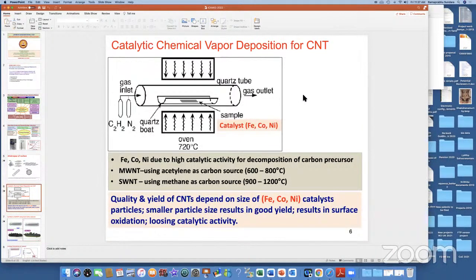So hydrogen will go out and carbon will get dissolved in the catalyst, and then one can grow either single-walled nanotubes or multi-walled nanotubes, depending on the temperature and the precursor that you use. For example, if you want the single-walled nanotube, one can use methane at high temperature, whereas for multi-walled nanotubes, one can use acetylene or ethylene as a carbon source at a lower temperature. The catalyst is iron, cobalt, and nickel. So, go to the slide show more.